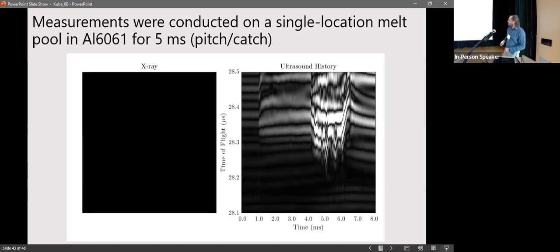So on the ultrasound response, each of these vertical time amplitude is the signal reflecting from the particular frame that was present over here. So if you look at this, this is the point where the laser turned on. This is the stable melt pool. This is the growth of the keyhole. This is the solidification, and this is cooling here. So there's tons of information encoded into this that we're using to back out fundamental information about your melt pool solidification, microstructure, and so forth.